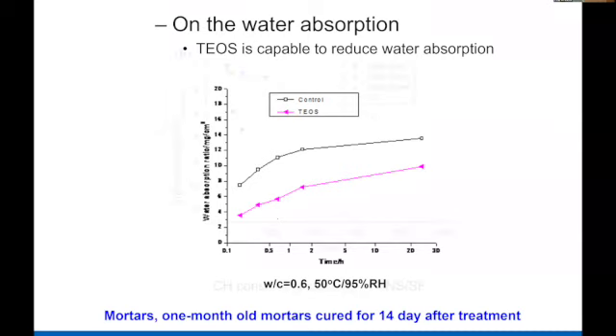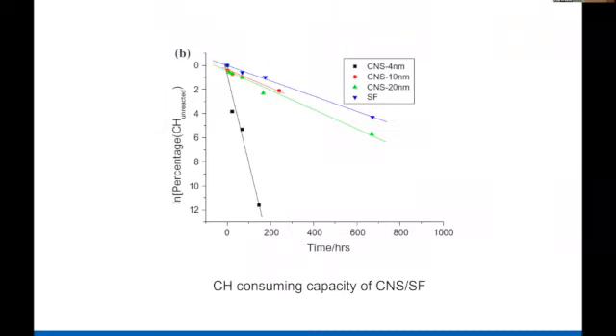I want to talk about what nanosilica does, which is different than, let's say, silica fume or microsilica. So one is the pozzolanic reaction. Here it's measured with the consuming capacity of calcium hydroxide. So you can see that when you have 4 nanometer colloidal nanosilica, the reaction is much faster. It's a couple of orders of magnitude, if you look at the slope, faster than conventional microsilica. So that's one reason, the advantage of using nanosilica.